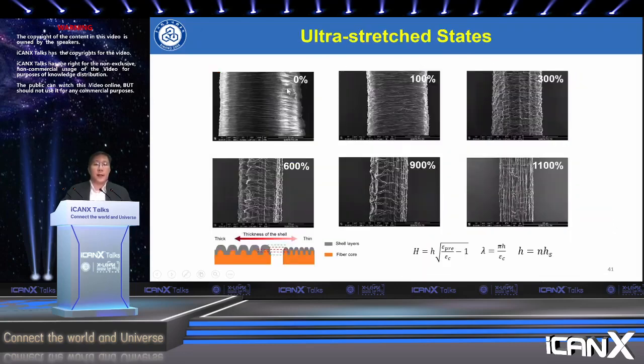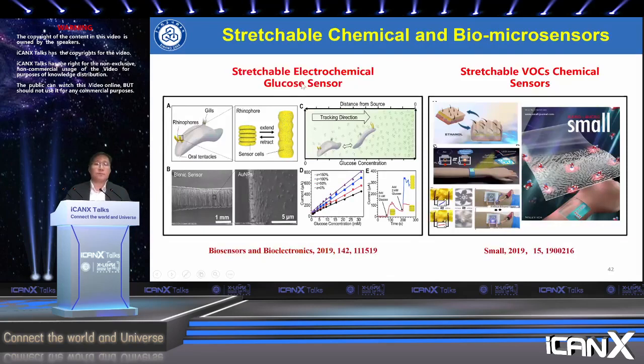You can see that at the different stages, at the stretched stage, up to about 11 times, the structure is very stable, and it's also very sensitive to the strain change, due to the contact state change of your conducting shells of the carbon nanotube composite films. And this method can also be extended to make stretchable chemical and biological microsensors. For example, in this work, we developed stretchable electrochemical glucose sensors with programmable sensitivities at different stretch states, and also stretchable VOC chemical sensors. If you are interested, you can look into these two papers.